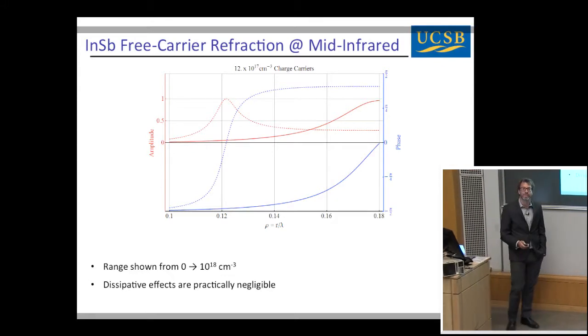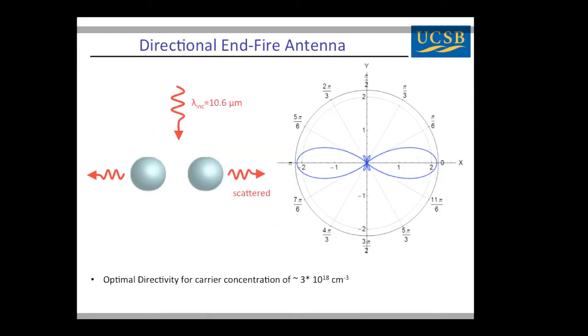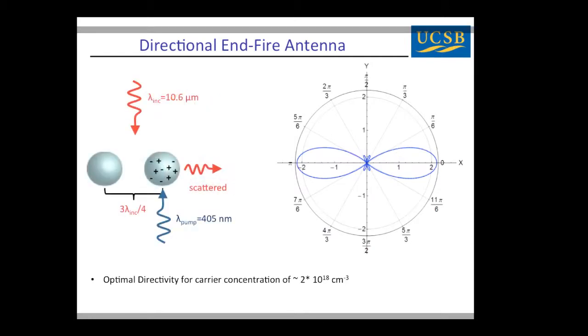Okay? So how might we use this type of effect? Again, we'll go to our simple 2-antenna system. If we start with, let's say, on the order of 10 to the 17 free carriers, we get a symmetric lobe. And then now, as we introduce free carriers into one of them, we get this directional lobe that appears. Okay? So the idea, again, is we're going to use interference between two particles to create a directional lobe. Okay? And this optimal directivity happens when we have about 10 to the 18 carriers per centimeter cubed.